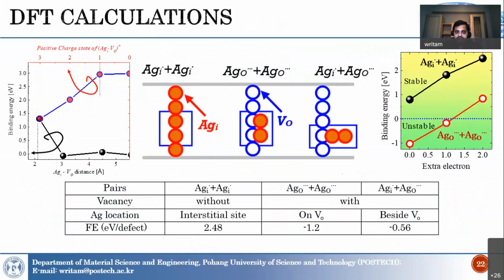The DFT calculation in this case shows that when the silver ions are very close to the oxygen vacancies, within a close proximity like 2 angstroms or so, it has a binding energy of almost 1.5.